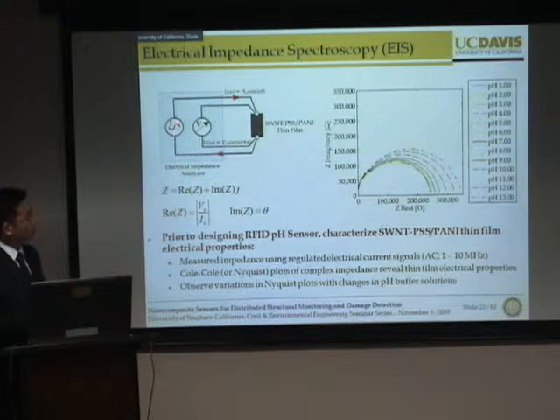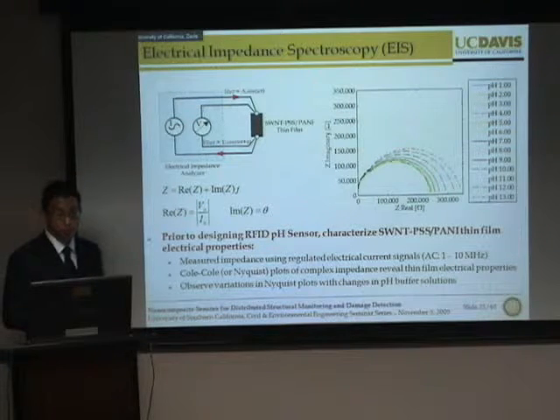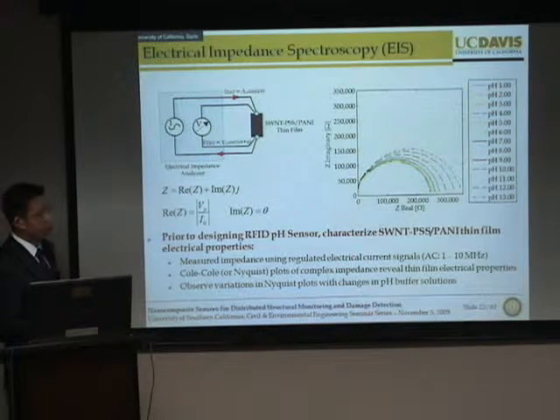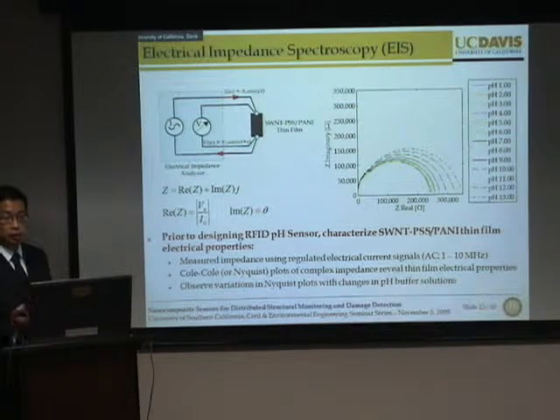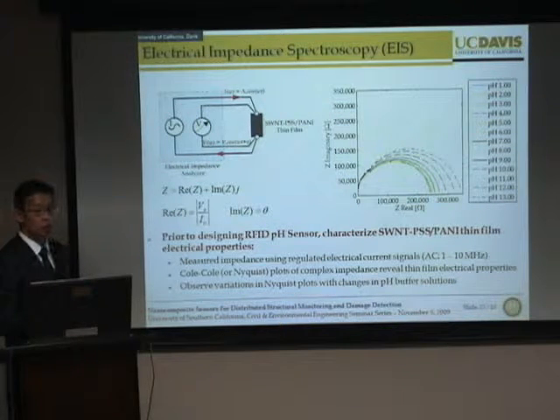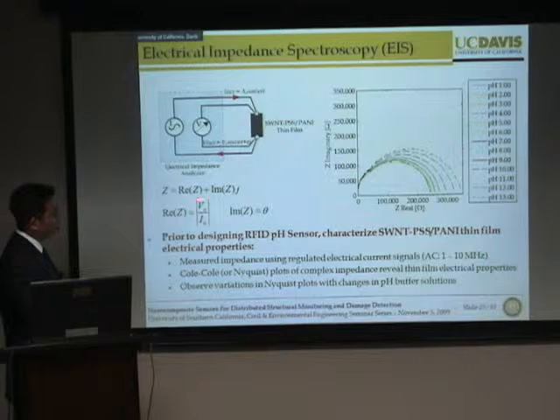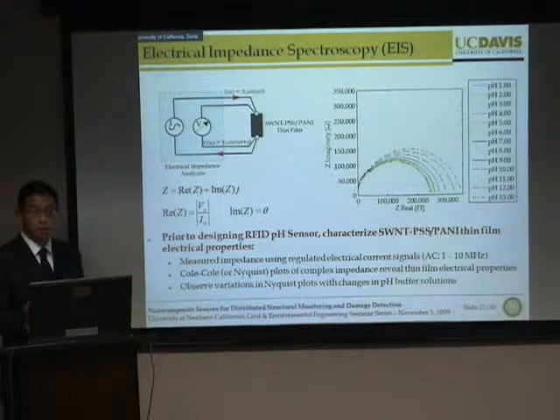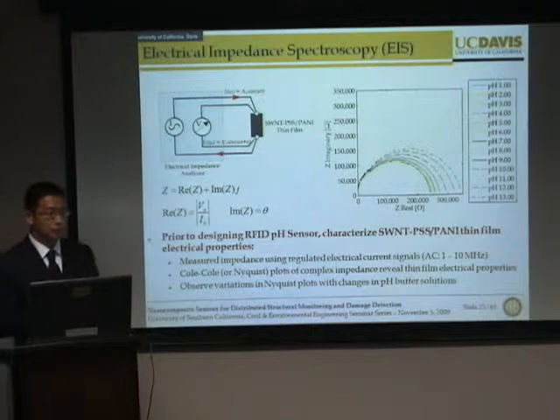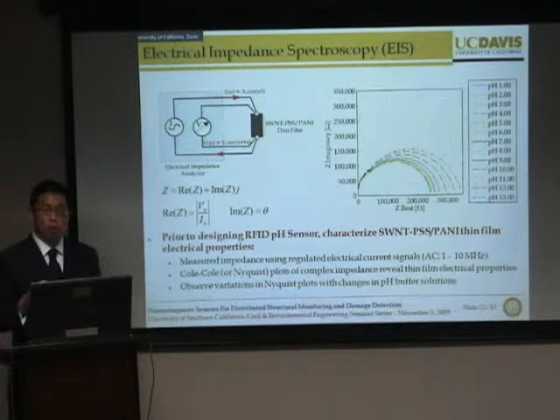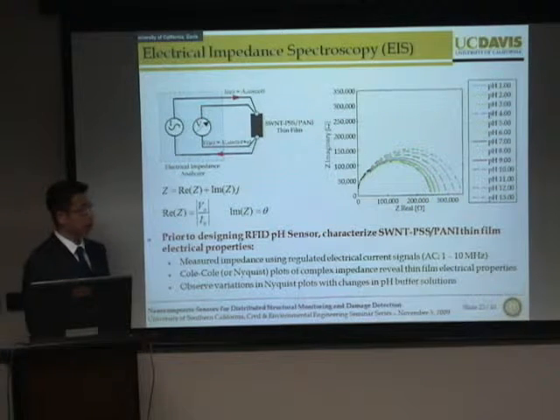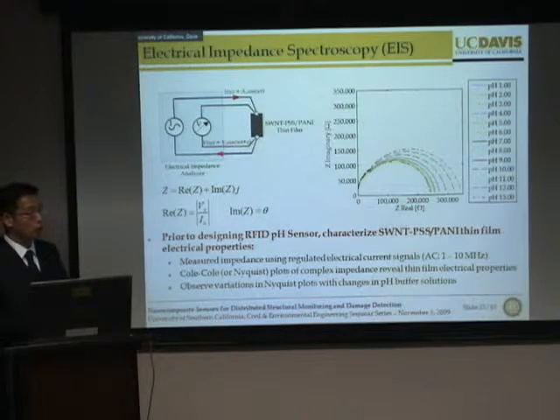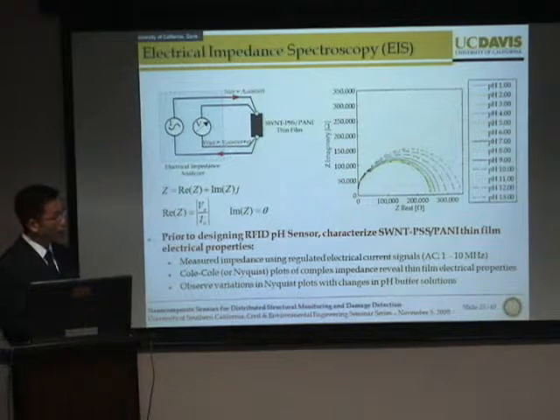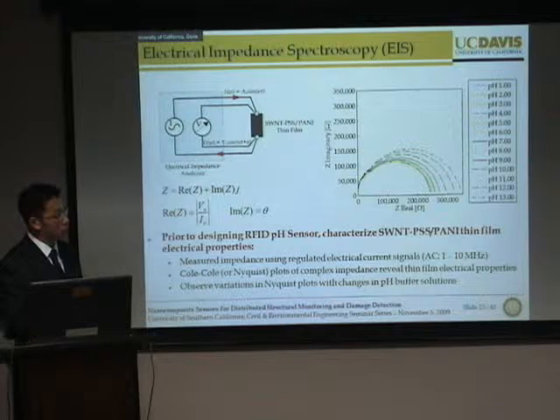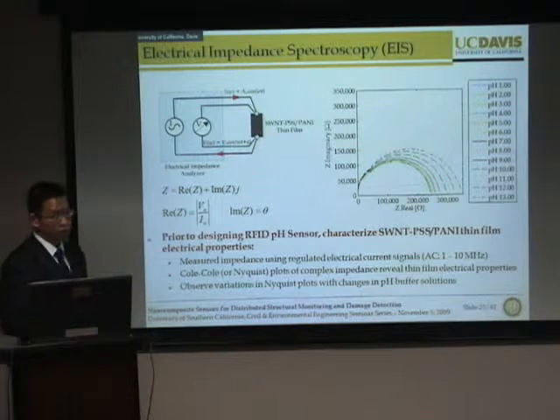Now, without going into too much detail, electrical impedance spectroscopy, or EIS, is very similar to a 4-point resistance probe measurement. But instead of applying a DC current to the material, in this case, we can apply a range of alternating current to the material. And instead of just measuring the resistance, we can measure impedance, which is inherently a complex quantity. And this impedance information that you get will be encoded with some resistive, capacitive, and inductive behavior of the material. So upon taking our pH-sensitive thin film, we then performed impedance spectroscopy on a number of these thin films subjected to different pH buffer solutions.